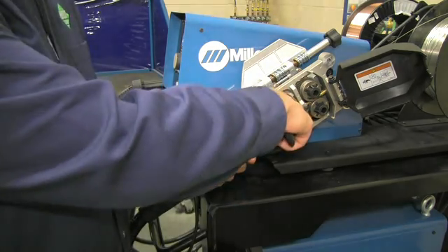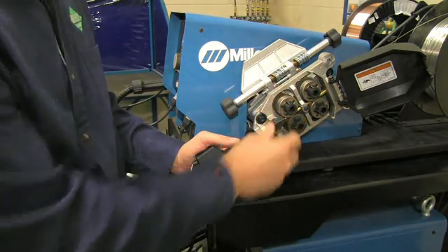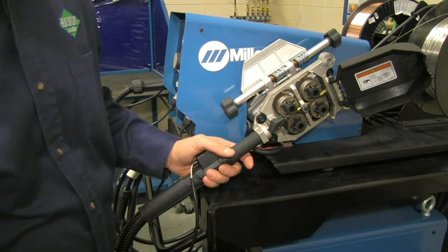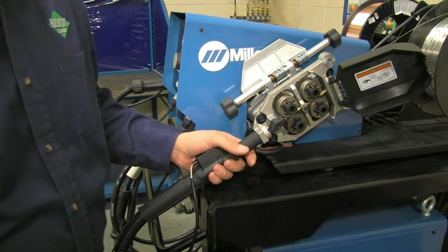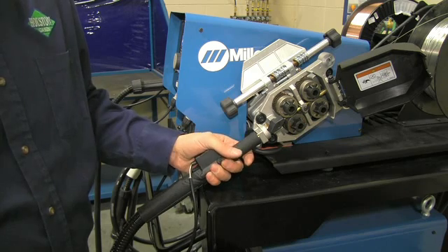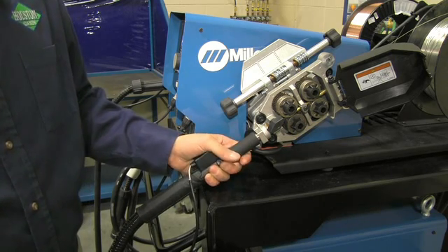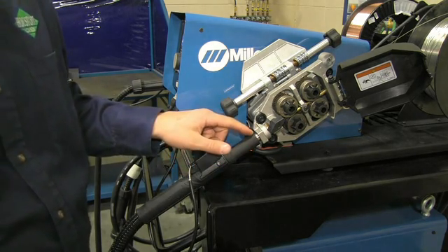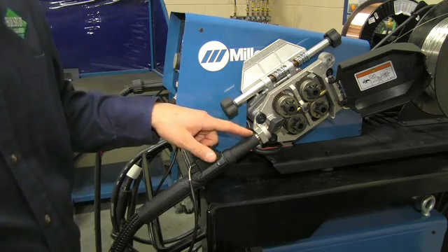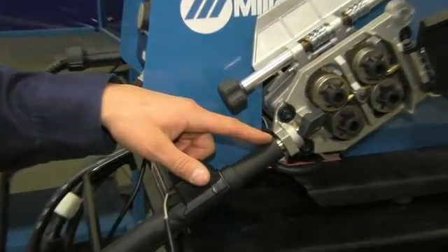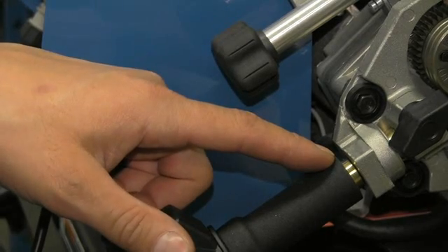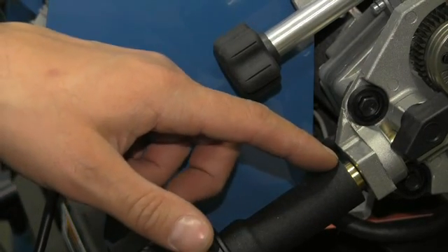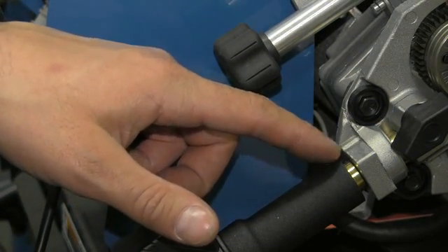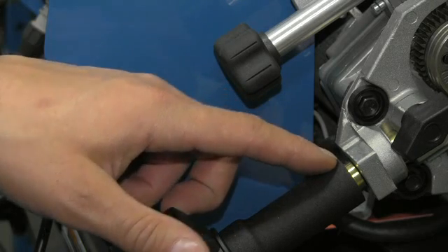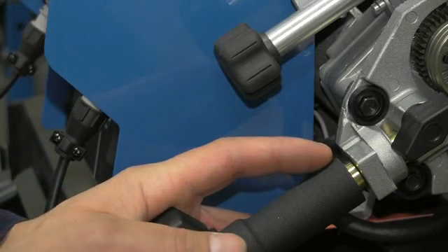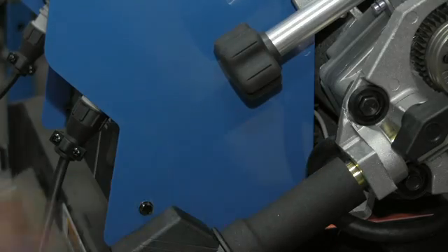However, what happens a lot of times is this nut doesn't get tightened down all the way. So it'll be semi-loose, and over about a day's work of welding, the gun will slowly start to slip out. As it slips out, the O-ring will become exposed, and you'll notice there's a little black O-ring right here. This O-ring will cause air to be aspirated into the gas line of the MIG gun, and this will always cause porosity. It's kind of hard to find because sometimes it's just barely sticking out.